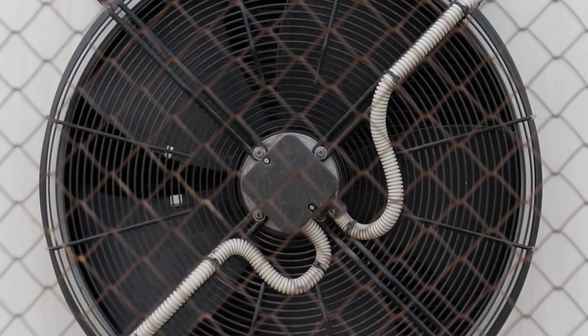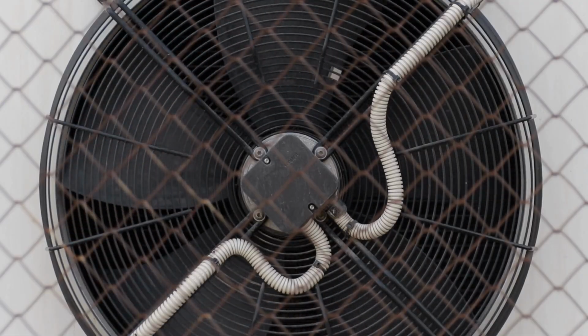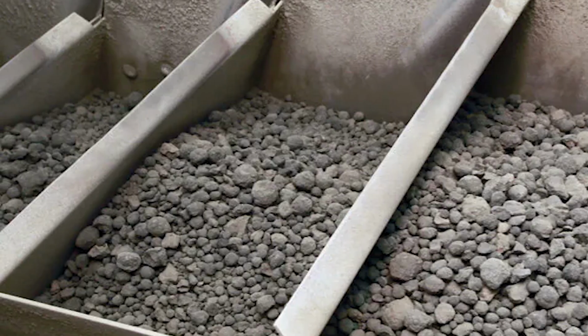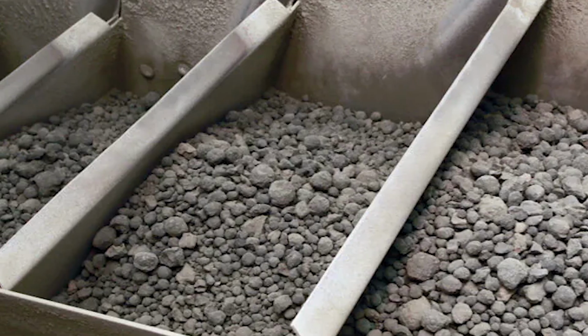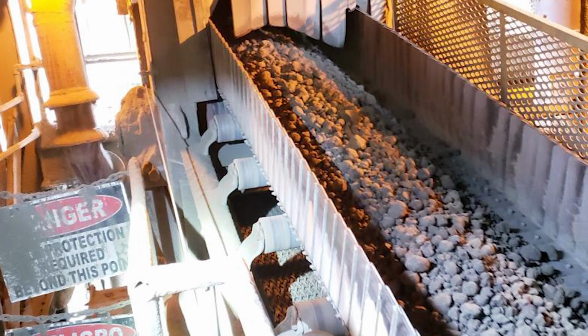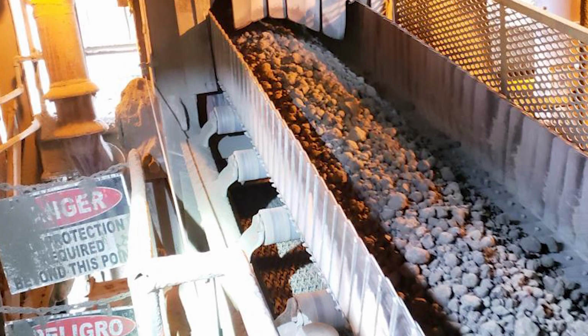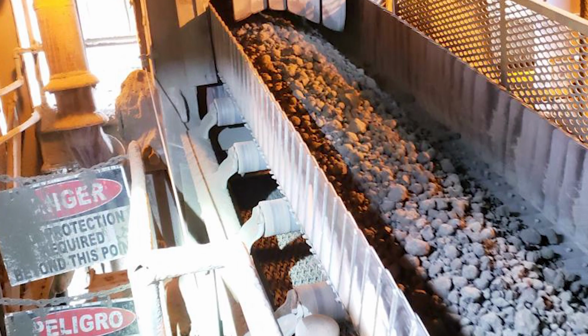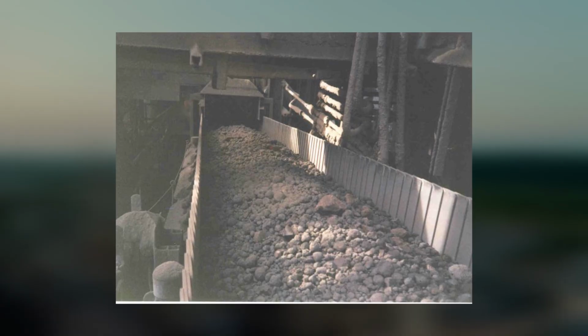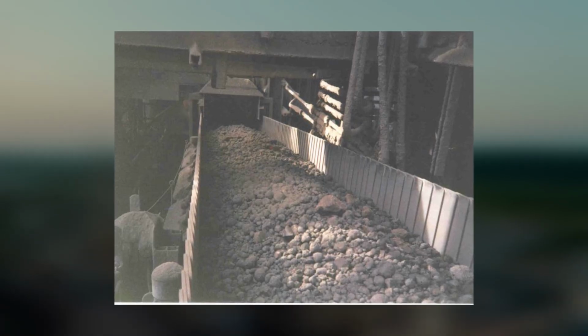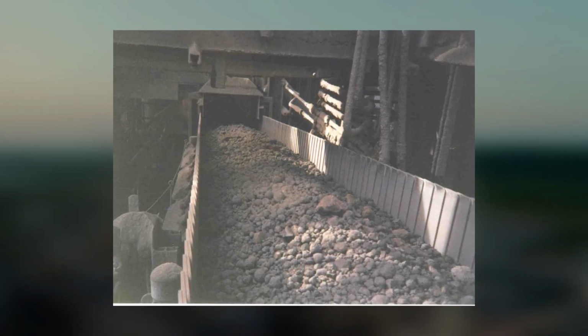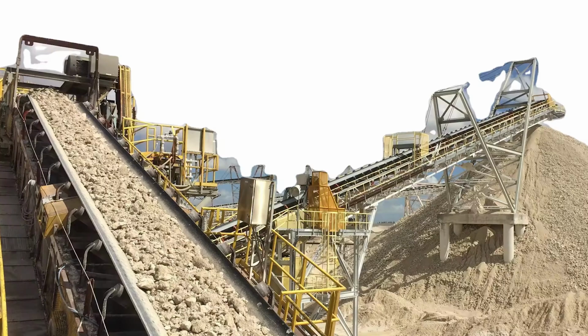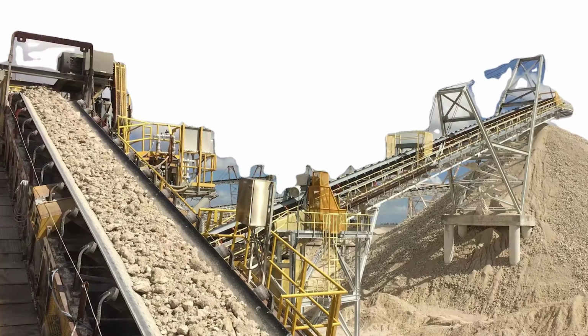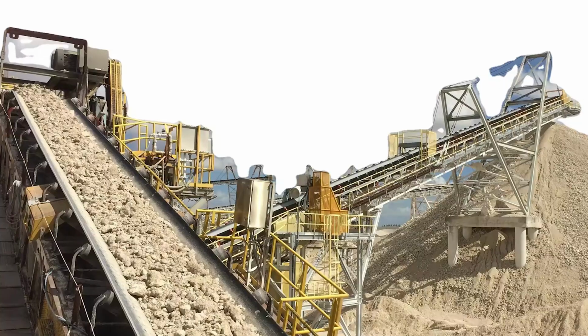To prevent this, cement plants use powerful cooling systems that blow large volumes of air through the hot clinker. Within minutes, the temperature drops dramatically, from more than 1,400 degrees Celsius to roughly 100 degrees. The hot air produced during this process is often recycled back into the kiln, improving the overall efficiency of the plant. Once the clinker has cooled, it moves to the final transformation stage.